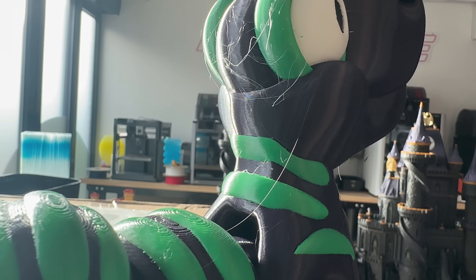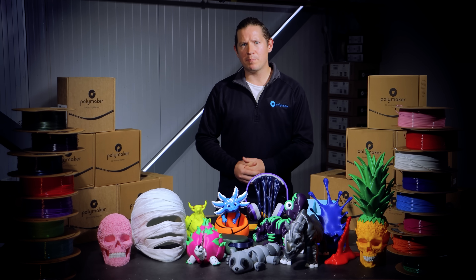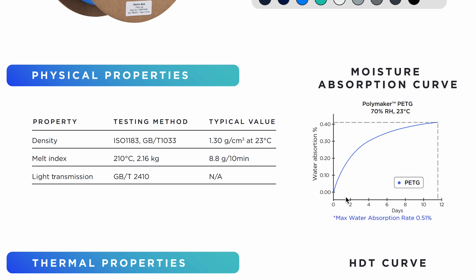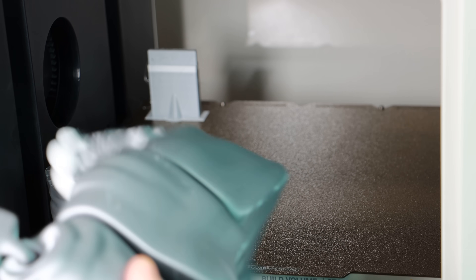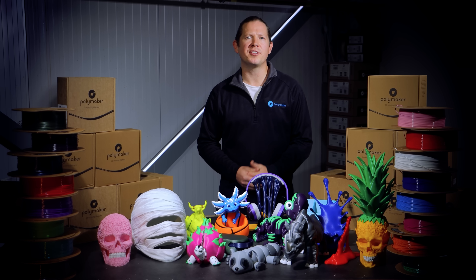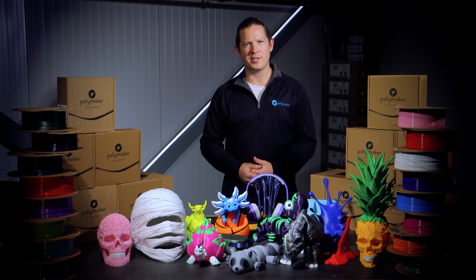This formula, like all versions of PETG, is still hygroscopic. Once you open the box, you'll notice an aluminium resealable bag, and as with every other Polymaker material, it's ready for perfect prints straight out the bag. The moisture absorption curve shows that while the equilibrium is quite low — around 0.5% moisture by weight — it doesn't take that many days to get there. I did notice some slight stringing after leaving fresh spools out on the Snapmaker over one weekend, but a few hours in the PolyDryer fixes that. 9 out of 10 problems with this filament are moisture related, so a quick blast of hot air usually fixes the problem.